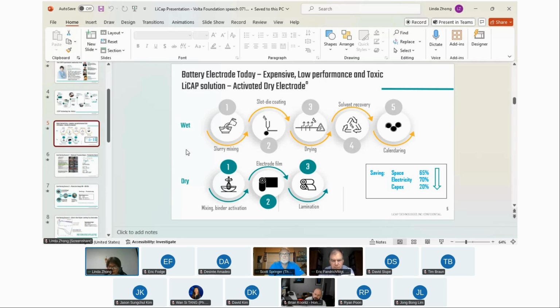By elimination, the machine became very small. Okay, you save space at least 65%. That's not including solvent recovery, because solvent recovery normally is outside of the building, so we don't count that. Even then, you reduce the space by 65%. Electricity you reduce 70%, because we don't have a dryer anymore. We don't have the solvent recovery anymore. The mixing is only 5-10 minutes now, so a very small amount of electricity. And the CapEx is reduced at least 20%. Okay.